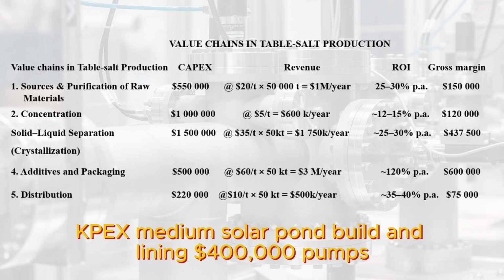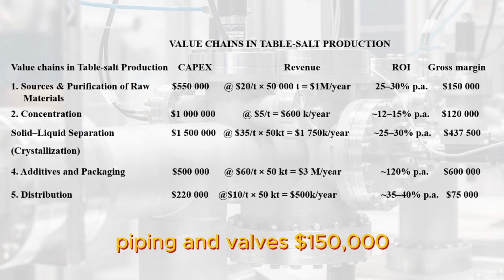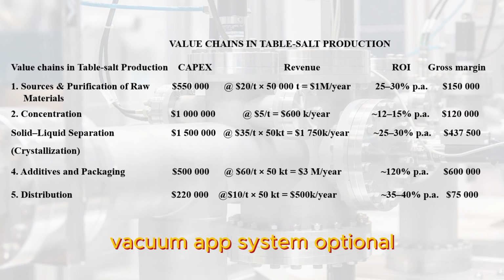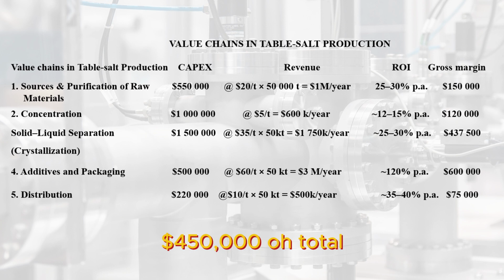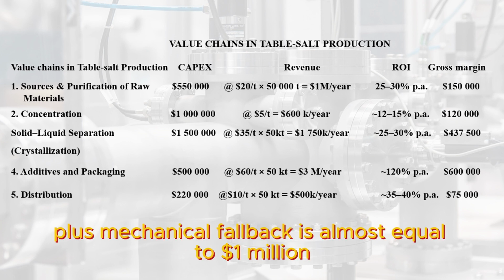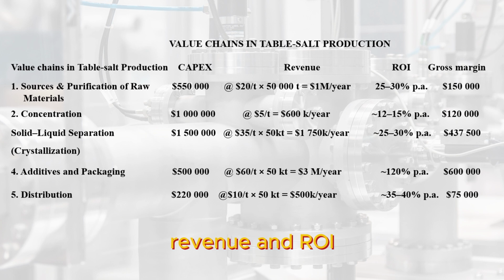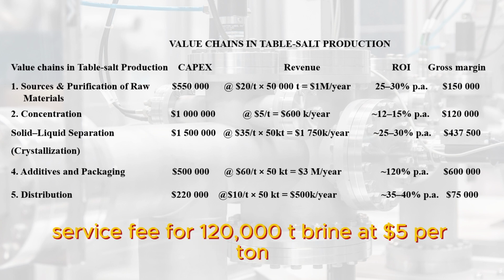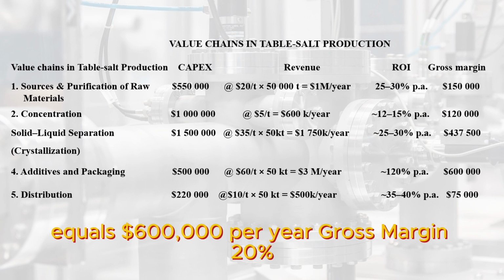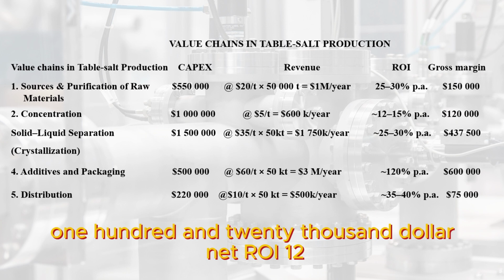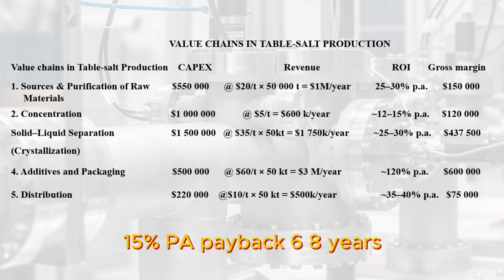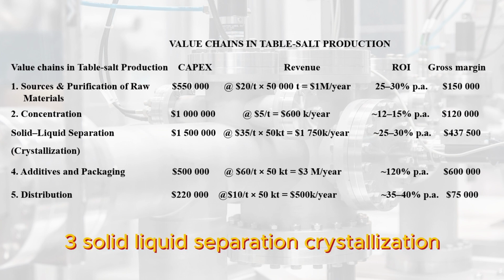CAPEX, medium. Solar pond build and lining, $400,000. Pumps, piping and valves, $150,000. VacEvap system, optional, $450,000. Total, solar plus mechanical fallback, is almost equal to $1 million. Revenue and ROI: service fee for 120,000 T brine at $5 per ton equals $600,000 per year. Gross margin 20%, $120,000 net. ROI 12–15% PA. Payback 6–8 years.